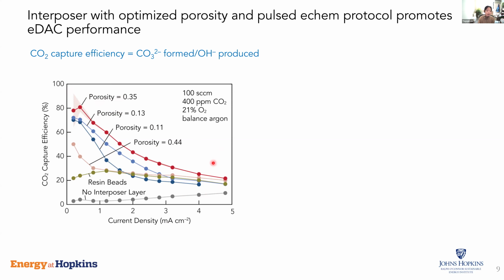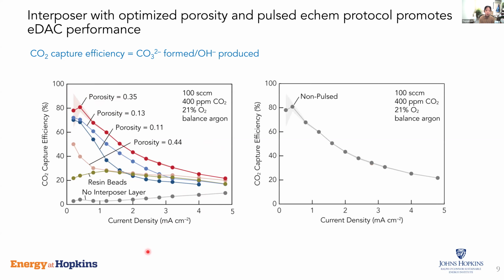So this is really promising, but as you can see, as we increase the current density, all this performance kind of converge to a lower value. So we think fundamentally there is some limit there, which we attribute to the relatively slow CO2 solubilization into the solution phase from the gas phase as we increase the current density. So because of that, we introduce an electrochemical protocol, which is pulsating our current. So we apply a current through a certain period of time to generate hydroxide, and then we stop the current to let the hydroxide transport and CO2 react, and then we repeat the electric current again.